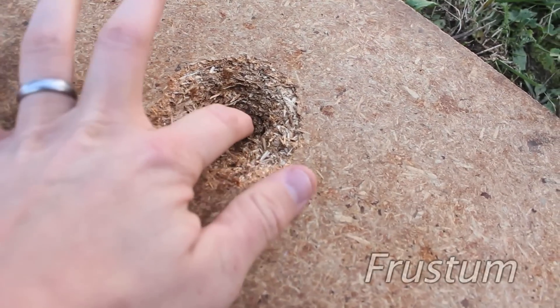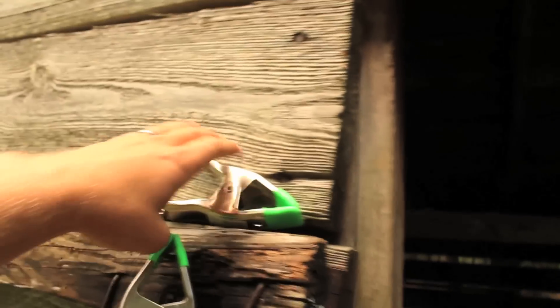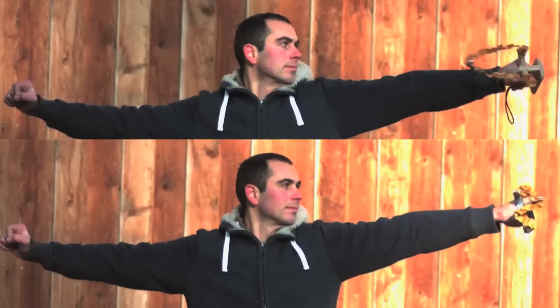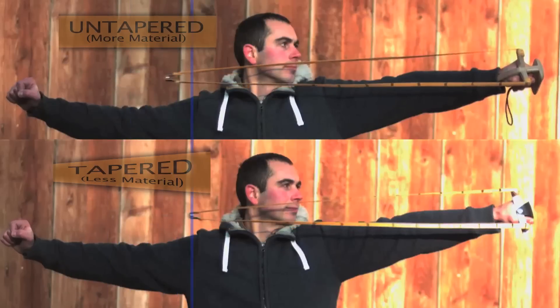Turn it around — it's interesting. How thick is this? This is a frustum. A frustum is when you try to distribute a stress throughout a material. Here I have two bands and they're C-clamped to the barn. As I go down the length of the band, you can see the one on the left is tapered to a smaller width than the one on the right. So clearly if I put weight on each of them, the one on the left you would assume would stretch more because it has less material resisting the stretch, right? So if we were to fire a slingshot with both a tapered band and an untapered band, I would assume that the untapered band would accelerate the projectile faster, right? No — that's not what happens at all. The slingshot community has known this for years, but they never had the rock solid evidence. So that's what Jorg and I did with the Phantom high-speed camera. We fired two different slingshots at a thousand frames per second. The one on the top is an untapered band, the one on the bottom is a tapered band. The top band is clearly accelerating slower than the bottom band.